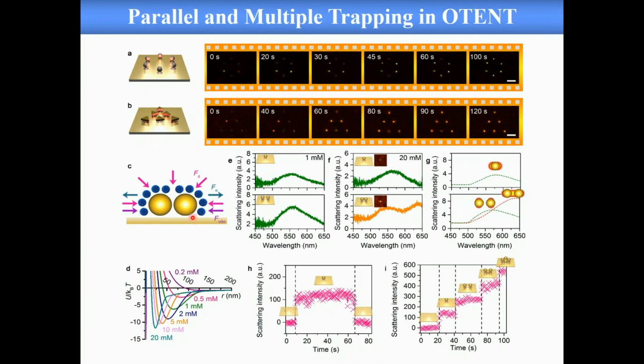All right, thanks. So when we bring 2 particles close enough, the distance becomes too small for them to hold the micelle between them anymore. This introduces an unbalanced concentration between the micelles surrounding the particles and the micelles between the particles. Because there are many more micelles surrounding this particle pair, a force pushes these particles together. We call this the depletion attractive force. This can be imagined as artificial bonding that we introduce between these artificial systems.